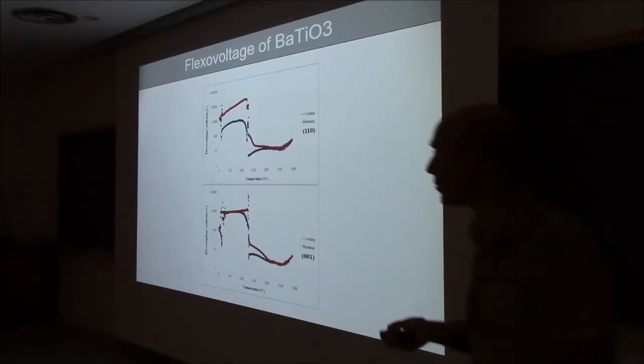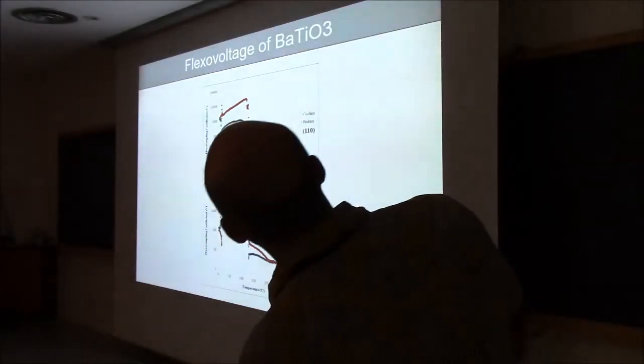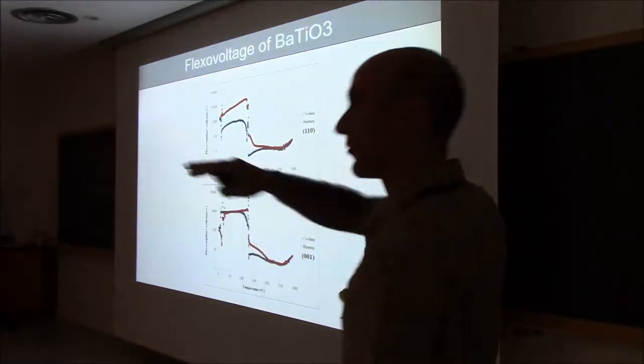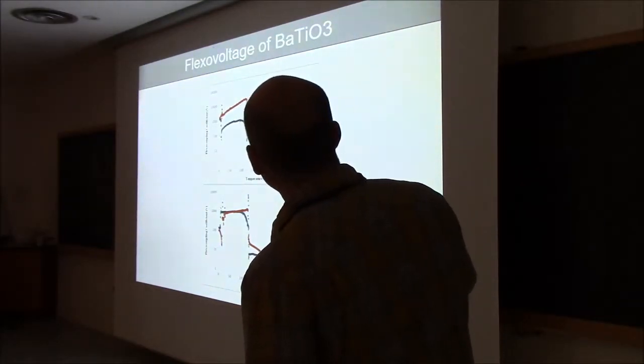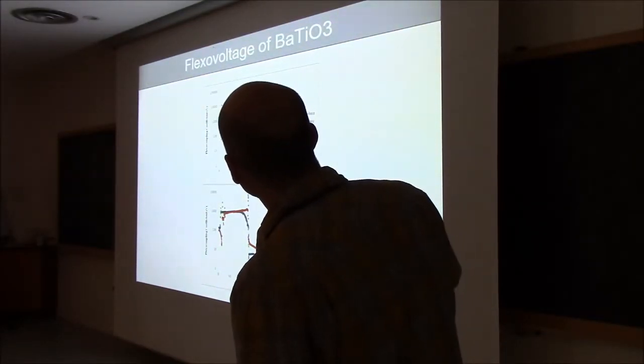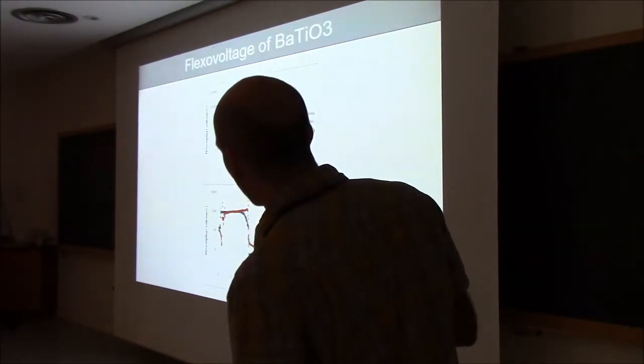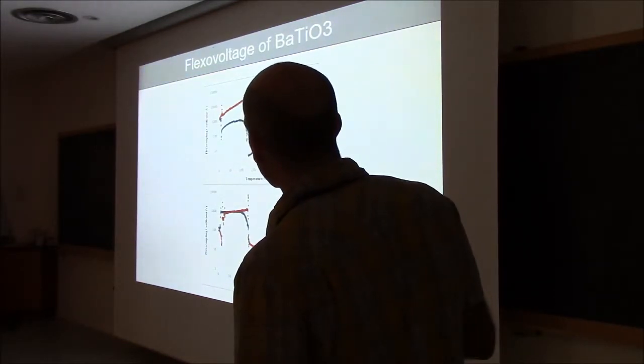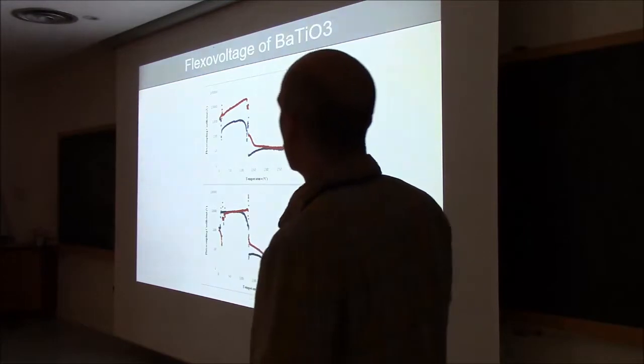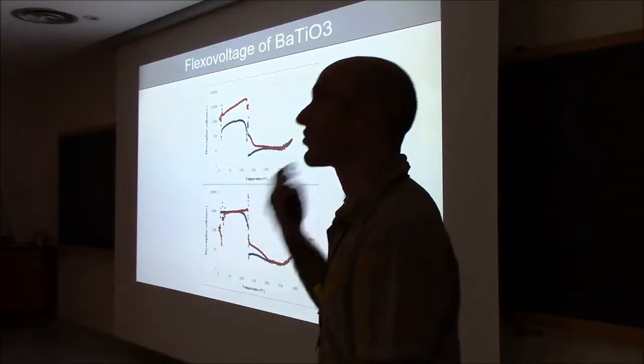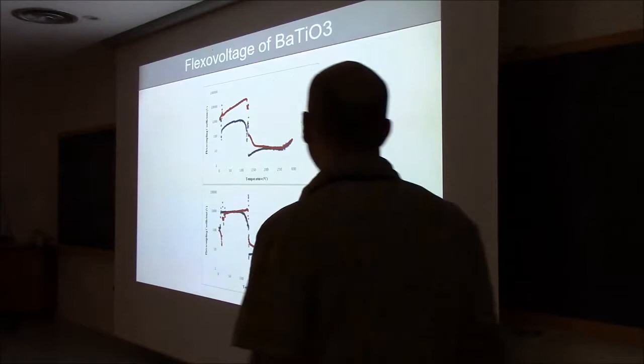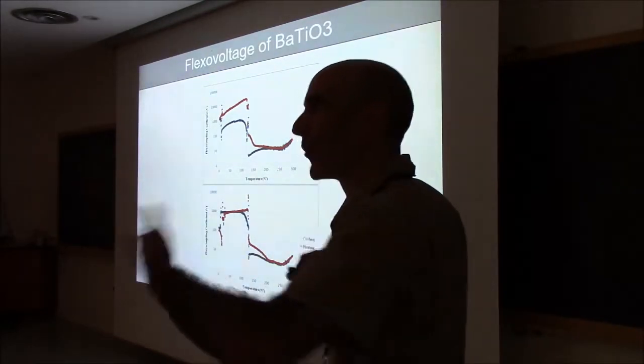Okay, and if you do that for BTO, you see the following. So the flexocoupling coefficient F, which is the flexoelectricity divided by the dielectric constant, indeed in the paraelectric phase is quite constant, quite flat. You can see 10 volts. Depending on the orientation of the crystal, you see some difference, but it's still flat. Then, below a certain temperature, you start getting some hysteresis and some temperature dependence. These we interpret as being a signature of the presence of polar nanoregions, and the amount of polar nanoregions depends on whether you're on cooling or on heating.